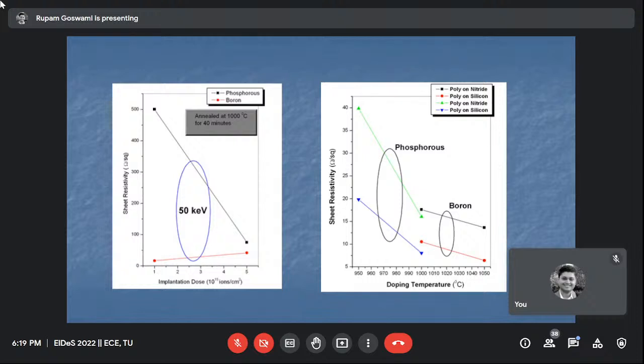In the case of phosphorus, the sheet resistivity decreases with implantation dose. This is very good, because the implantation dose is first 1 times 10^15, and then 5 times 10^15. If we produce higher impurities, then the sheet resistivity will of course go down. But in the case of boron, there is a slight increase. You know why? Because these are boron doped grains of polysilicon, and those are phosphorus doped grains. So the effect of grain growth is reversed in these two cases, and that effect is coming over here. When there is a change in the grain size, this will bring a change in the piezoresistive coefficients of the film.